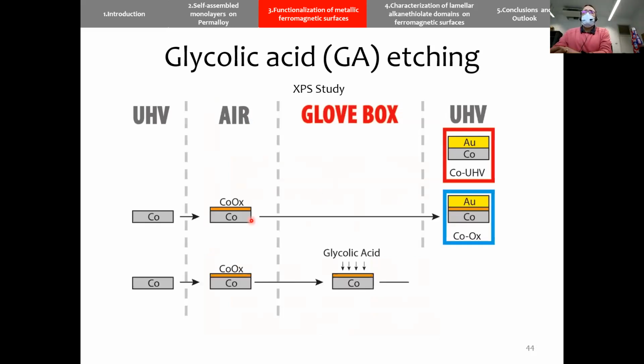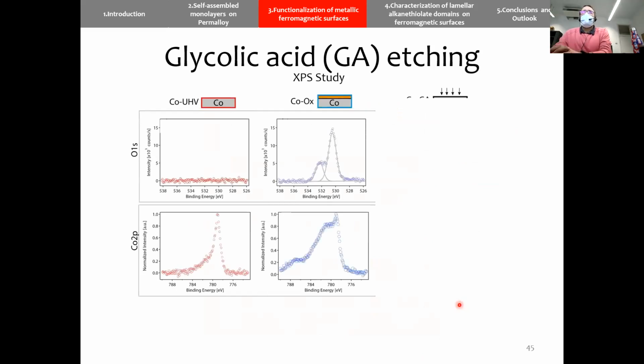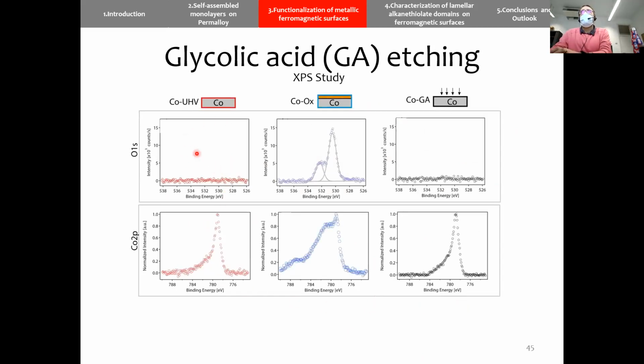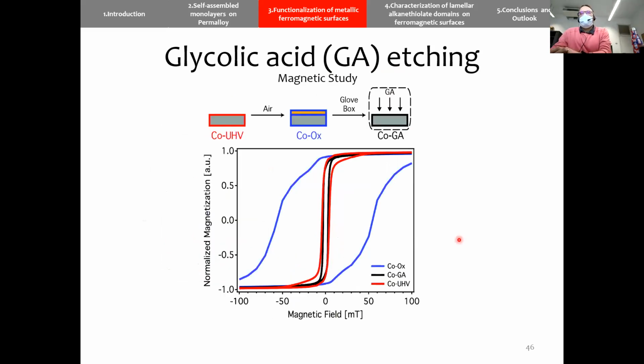And by XPS, we also wanted to study a reference sample, an oxidized sample, and a recovered sample. By XPS, we can observe that no oxygen is present in the reference, as also in the sample we exposed to the glycolic acid. And also we can see that the cobalt signal corresponds to a metallic bulk. The magnetism also speaks clearly. We have the same hysteretic values, the same coercive field, from the reference and the treated sample.